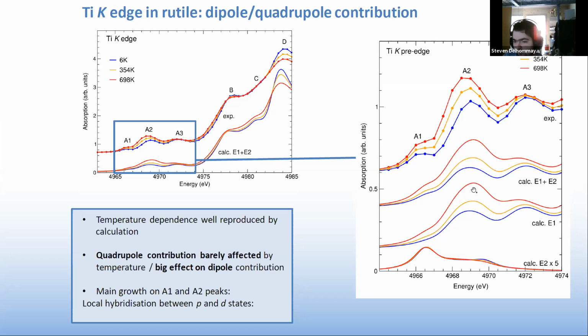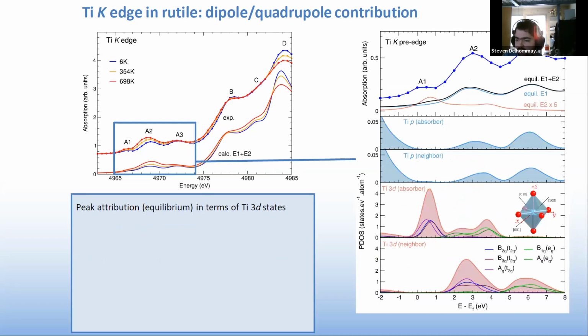And once again, our best bet is going to be the projected density of states. So once again, I show them to you. Just like for aluminum, here we have the experiment that is compared to the equilibrium case. So the E2 and the E1 contributions at equilibrium, the black line being just the sum of the E1 and E2 contributions. And below that, I show you respectively the absorbing Ti and the neighbor Ti P states, and then the absorbing Ti and the neighbor Ti 3D states.